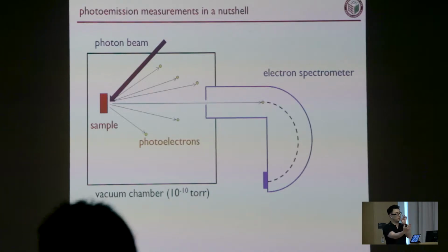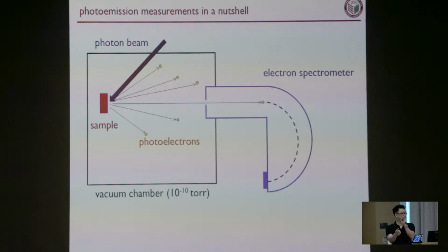The orientation of your sample relative to the direction the pinhole is facing determines the direction, the angle, of the electrons coming out. If you measure the speed of the electrons using simple electrostatic plates, you get the energy. So now you have the energy and the directions, and you can back out the momentum of the electron relative to that of the sample.